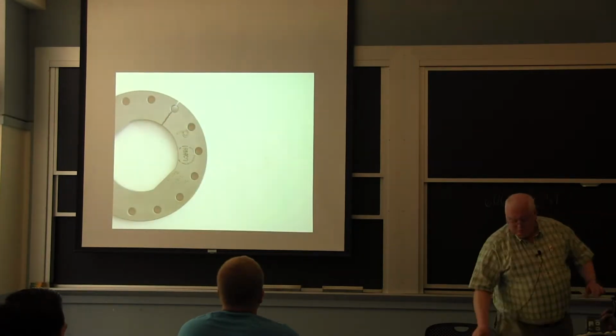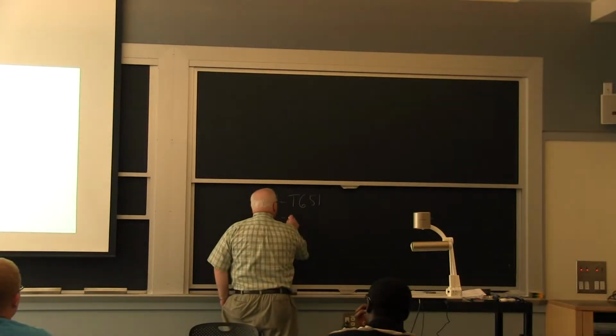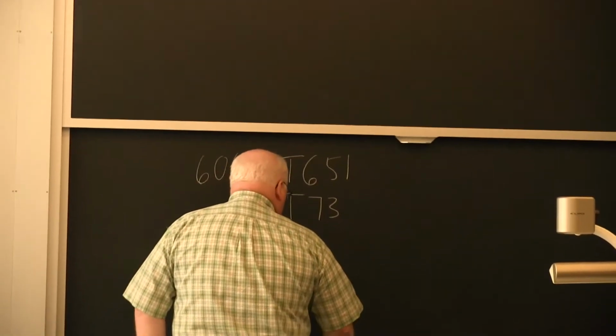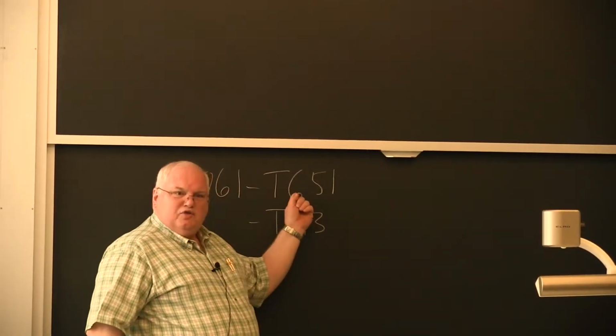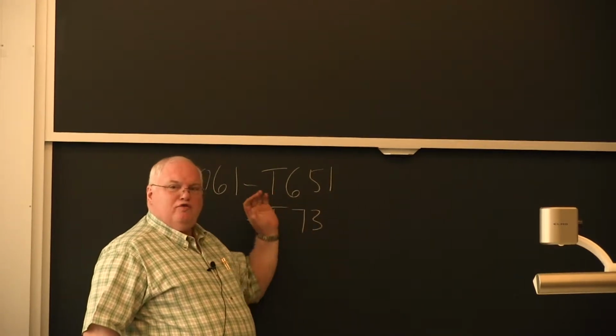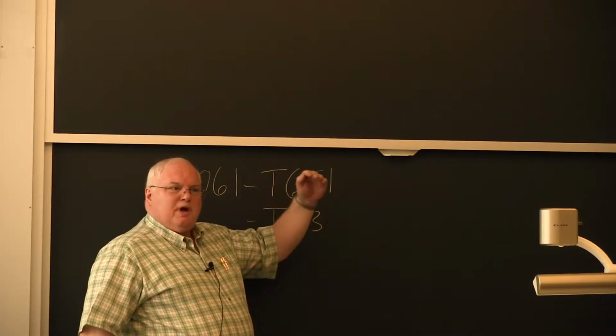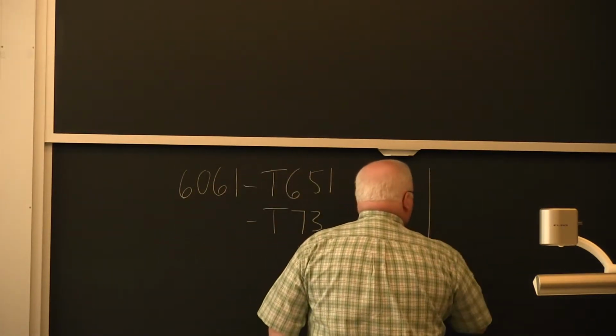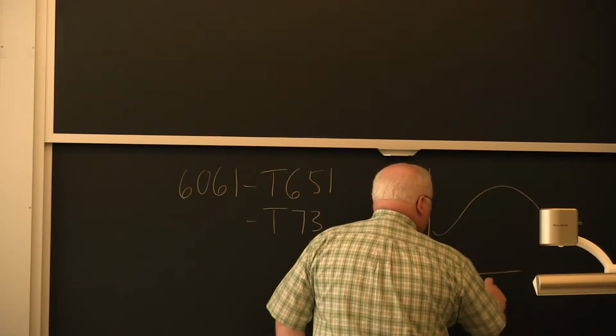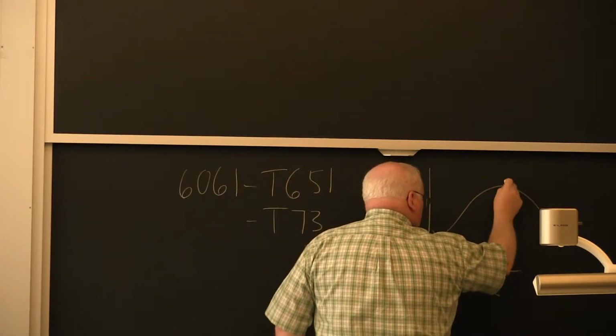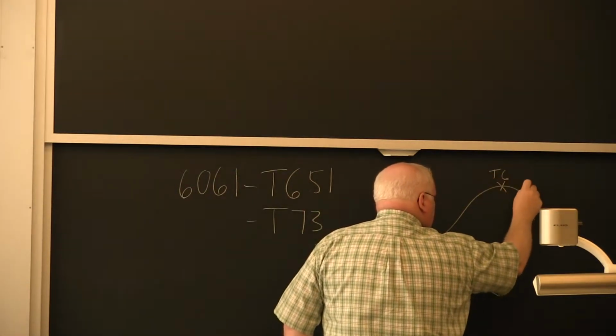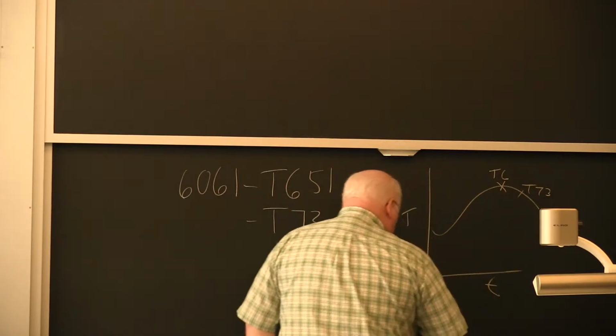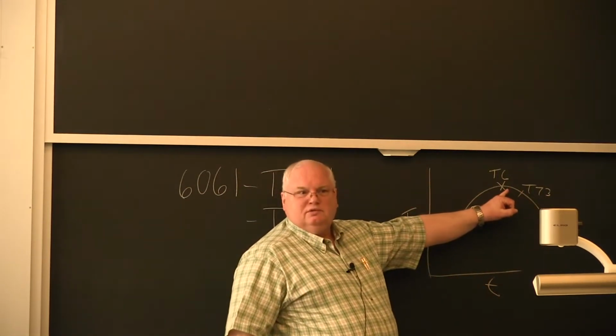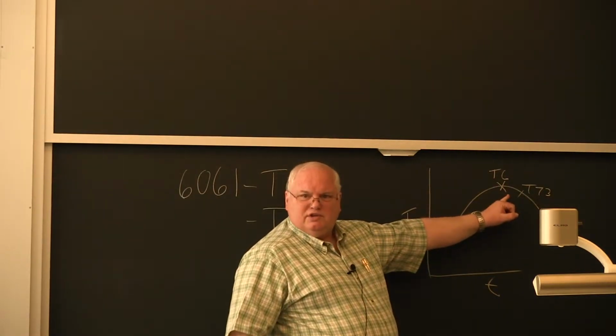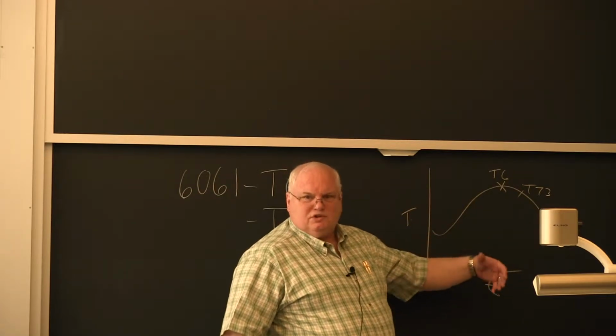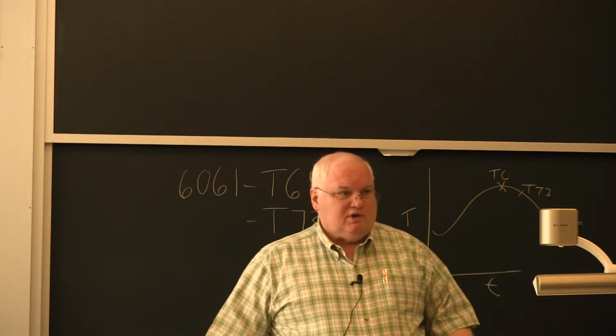Sikorsky says, oh, we shouldn't have been using the T6 heat treatment. We should have been using the T73 heat treatment. And T73 is a heat treatment that is actually overaged. You go past the peak strength and you get about 10% lower strength. If you look at the tempering curves for aluminum, they'll kind of go like this. This is time versus temperature. This is optimum age, that's T6, and T73 is the temper that's just passed by about 10%. But the toughness like doubles, okay? And the stress corrosion cracking resistance increases by about a factor of 2 on stress, which is like a factor of 10 on life in terms of corrosion fatigue.